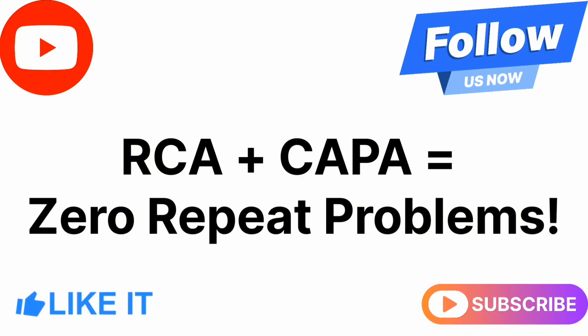They did not guess, they did not assume. They collected samples from every stage: raw material, pigment, carrier resin, additive, extrusion processing, cooling line, pellet inspection, and finished product. They checked MFI, they checked moisture, they checked dispersion, they measured delta E, they reviewed the production log. They even compared shift-wise machine parameters. For 6 hours, every possibility was investigated. Finally, they found something nobody expected.